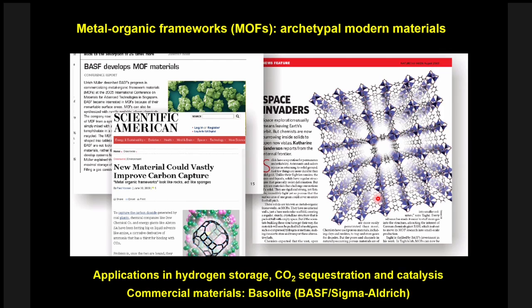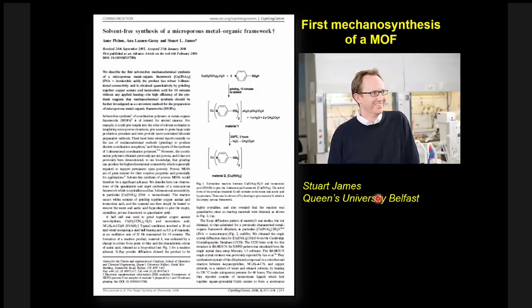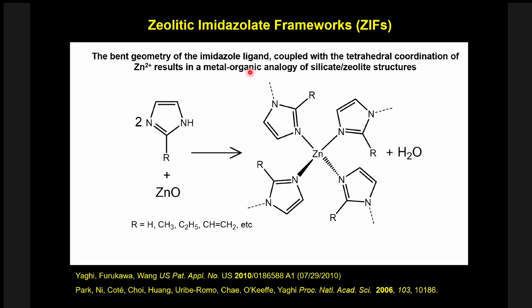Mechanochemistry of MOF synthesis is not something we invented. It was actually first introduced by a really, really well-respected group in the field, led by Stuart James at Queen's University in Belfast in the UK, who reported the first mechanosynthesis of a MOF material, I believe 2006. Check out, this really is the first paper. And our interest is not so much in making MOFs, but making MOFs from the simplest precursors, right? So remember, we want to take those rocks, carbonates, oxides, maybe even silicates or something, and turn them into metal organic frameworks. And here is an example of some chemistry we do.